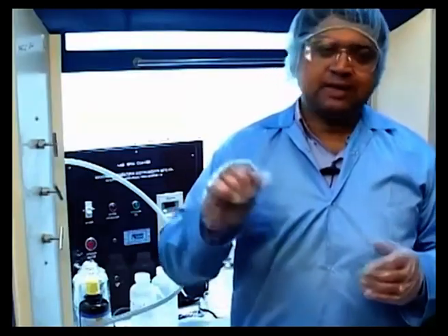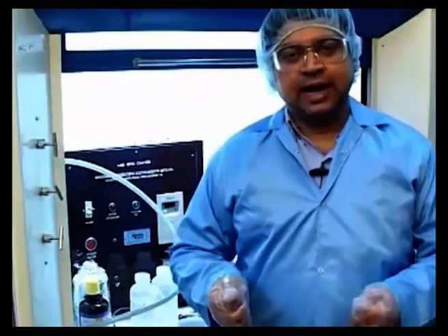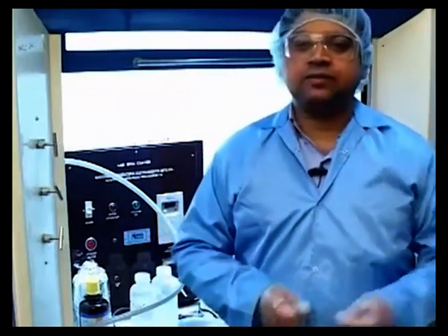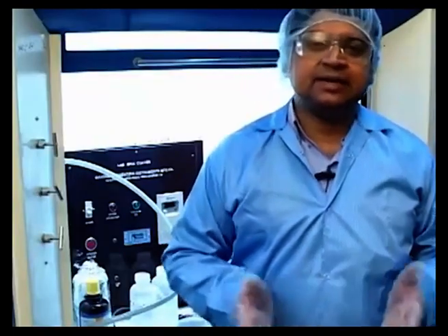And once the solution stabilizes a little bit after mixing, we typically use a glass rod to stir the solution and put the wafer in the solution and clean it for several minutes, about 6 to 7 minutes, so that everything which is organic on the top goes away. And then the idea is to extract the wafer back and rinse it using DI water a few times so that you can remove the acidic impurities, and then dehydrate it in an oven set at 95 to 100 degrees Celsius. So let us look at that process now.